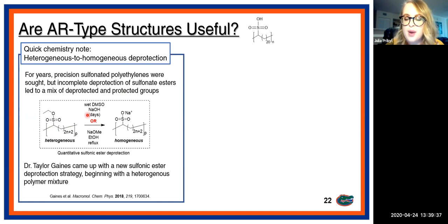So this is what we call in the Wagner group beach chemistry, because you set it up and then you go to the beach. And when you come back, you see what happened. So in this case, what happened was he came back to a completely homogeneous mixture of the deprotected sulfonate polymer in DMSO. And the reason for this is that as the sulfonic esters become hydrolyzed to this form, the polymer became more and more soluble in the DMSO.